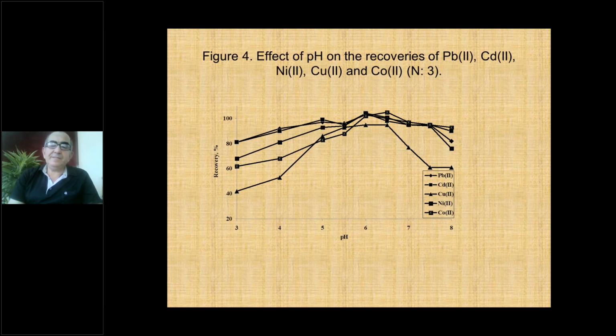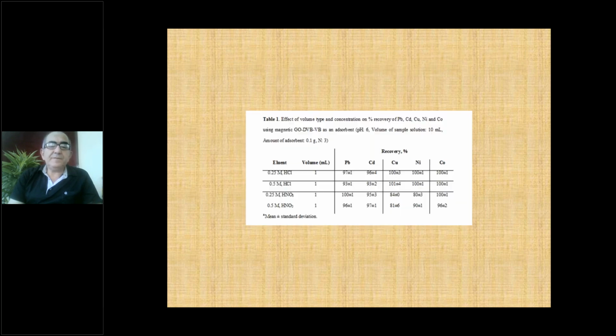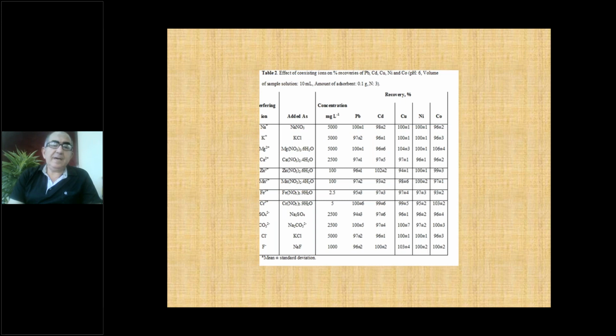And we got quantitative results at pH 6. Then we used different eluting solutions for the desorption of our analytes from the new materials, including nitric acid and hydrochloric acid. We have quantitative results, so we can use these eluting solutions for the desorption of our analytes from the adsorbent. Then these are the effects of interfering ions on the recoveries of our analytes. As you can see, high levels of sodium, potassium, magnesium, and others did not affect the recoveries of our analytes.